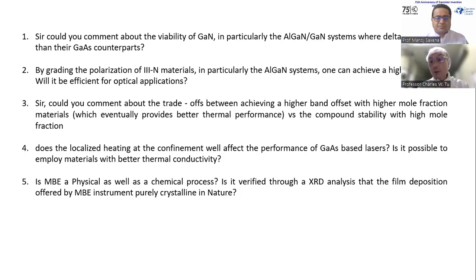About the second question, as long as you increase the delta EC, and if you use this material as a quantum well, then it should be the same. The larger the delta EC, the higher the temperature of operation. And so it will be good for efficient optical application. Trade-off between achieving higher band offset, higher mole fraction, versus compound. Yes, so this is what I was talking about. It is a challenge of this dilute nitride, because we want more nitrogen so that we have a smaller band gap, larger band offset, but then we have more defects.